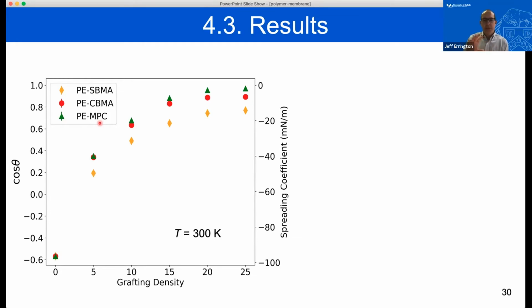So one of the things that you notice relatively quickly is that even a modest grafting density, 5 tethers in this case, has a relatively significant impact on the change in the wetting properties associated with the system. So the base system is highly hydrophobic in this case, a contact angle that's greater than 120 degrees. And then by introducing 5 polymer tethers in this case, you take the contact angle to something that's significantly less than 90 degrees. As you add additional polymer tethers, you have sort of diminishing returns. In this case, the system gets very, very close to the wetting point once you get to the vicinity of 20 or 25 tethers added to the system.